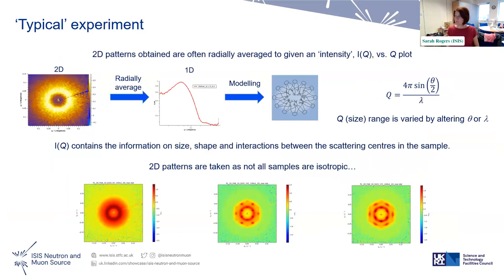So a typical experiment, for those that don't know, we tend to measure everything on these big 2-dimensional detectors. The ones on SANS 2D, for example, we have 2 times 2, like 1 meter squared arrays, about 8 millimeter size pixels. We take those 2D images, but often what we do is collapse those down. We radial average it, collapse it down into a 1D image where you basically get intensity versus Q, or the size that you're interested in. That intensity contains information on the size, the shape, and the interactions between the scattering centers within that sample.